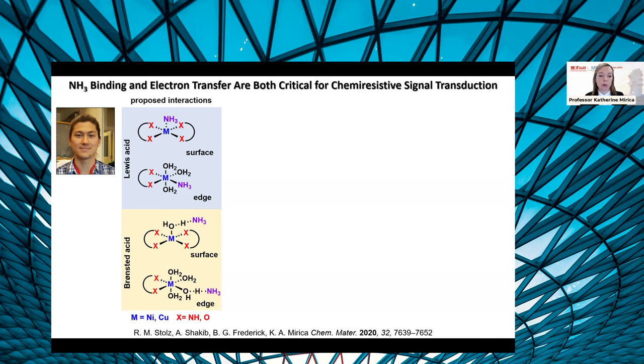In our devices, we have metal bis-dioxolene linkages in the devices that I've looked at so far, where X is oxygen. And we envisioned that in these types of interactions, we may be able to have Lewis acid interactions where the analyte can interact directly with the metal site of the framework material, as shown here, but also Bronsted acid interactions if water ligands are present on the surface of this material and are coordinated to the metal centers. Both of these types of interactions, Lewis acid or Bronsted acid, can be visualized as being on the surface of the material, so on the basal plane, or on the edge sites.